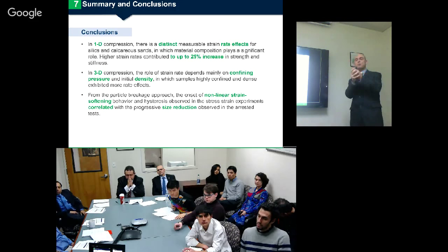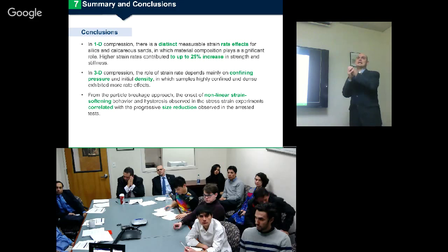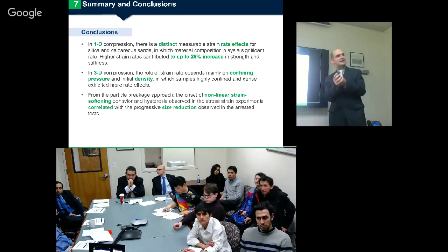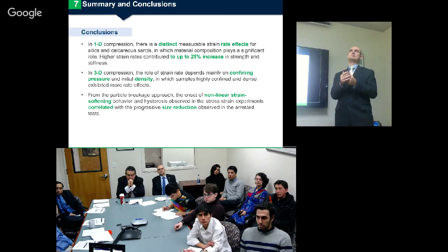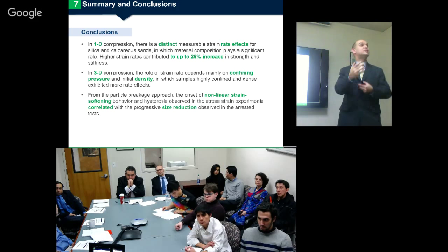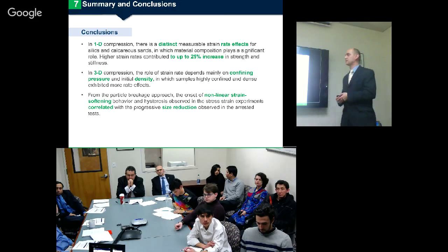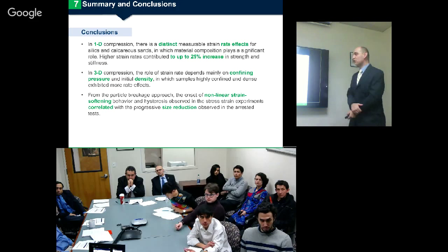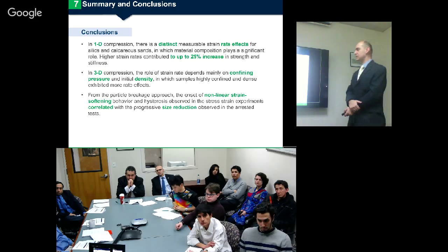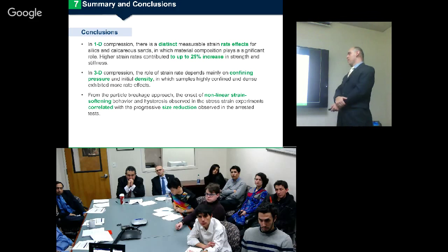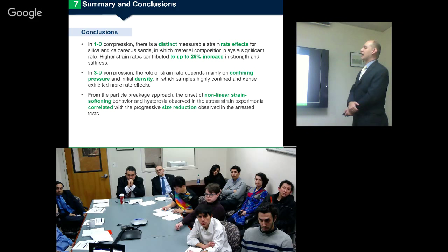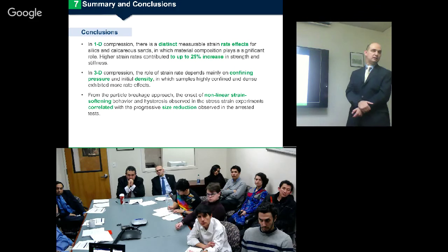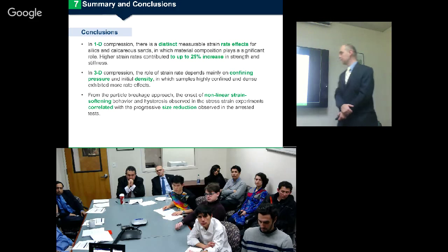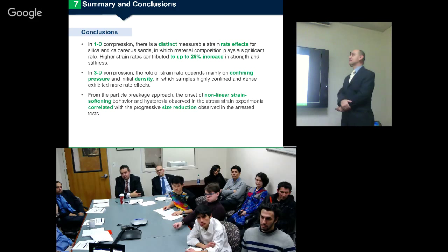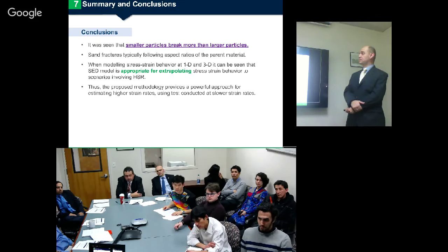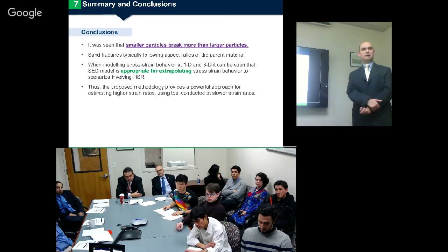Which means that when the sample is highly confined and is prepared at very high density, there are more chances that the strain rate effect will be observed. And from the particle breakage approach, the onset of nonlinear strain softening behavior observed in the triaxial experiment correlates with the progressive size reduction observed in these arrested tests. It was seen important that smaller particles break more than larger particles.